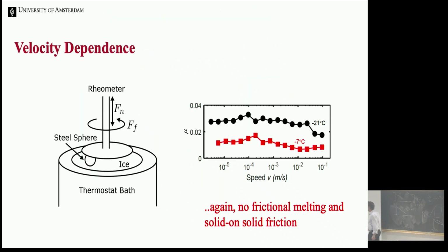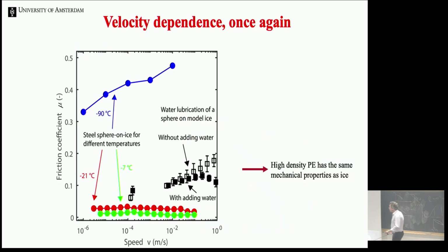Again, it's not lubrication. I showed you the Stribeck curve. These are values as a function of velocity, and as I said, it's easy to do 1, 2, 3, 4, 5 orders of magnitude in velocity, and we find no dependence of the friction coefficient on the velocity. Then there's a dependence, of course, on temperature. But this indicates again that what we're looking at is solid on solid friction and not some kind of weird lubrication. At very low temperatures, it becomes complicated, and I will come back to that at the end of my talk.